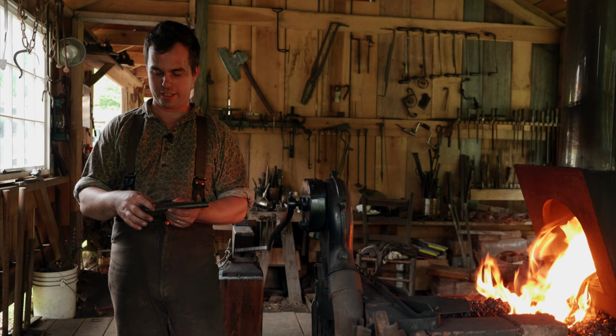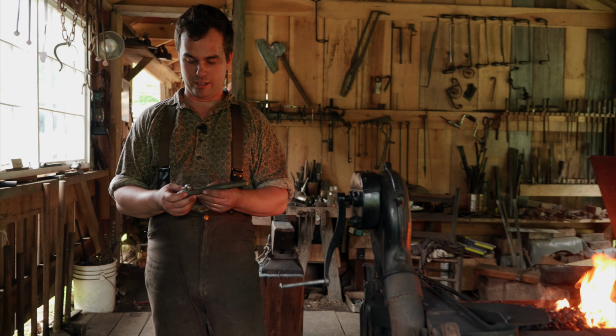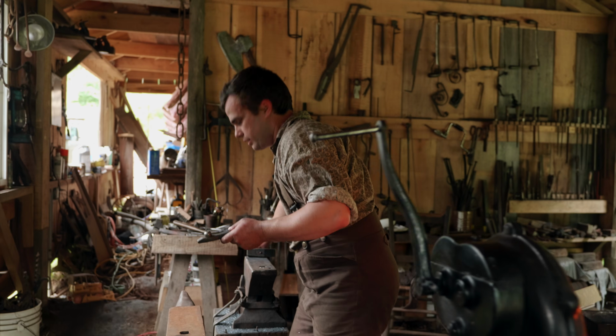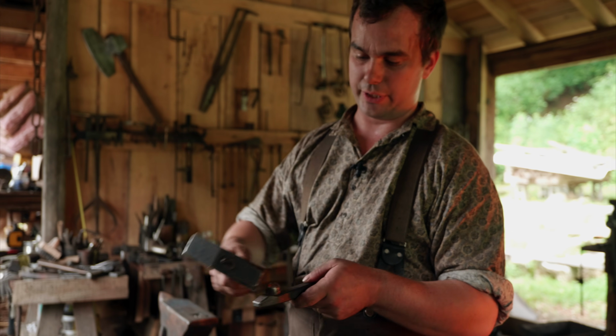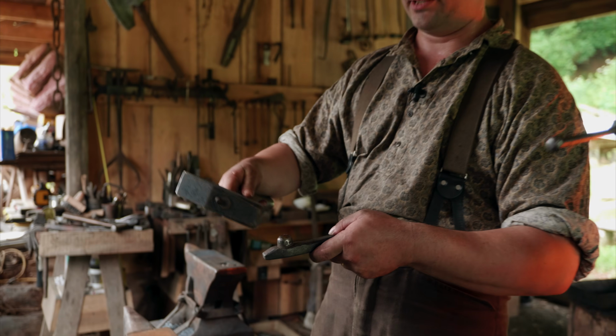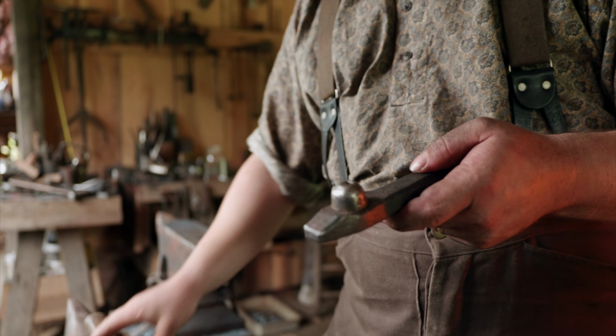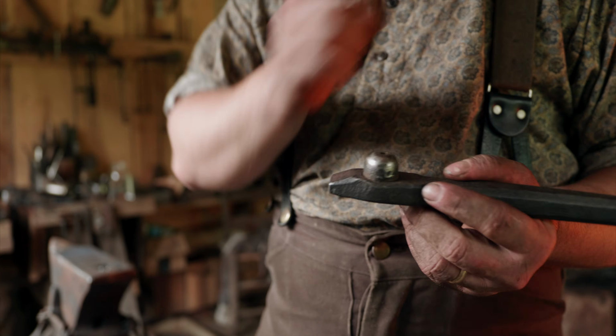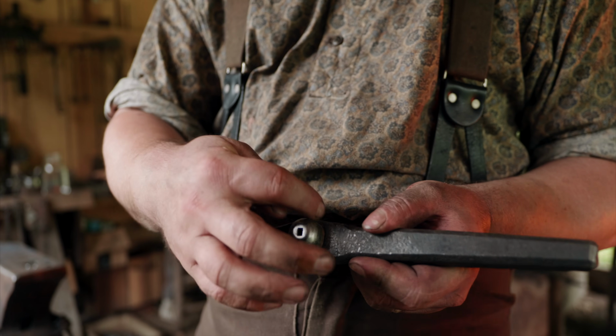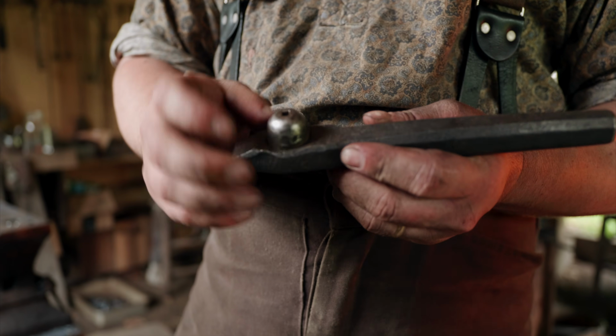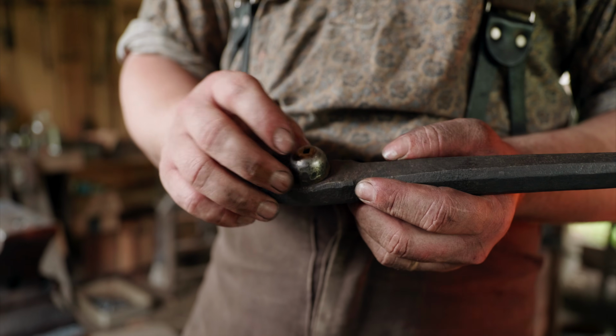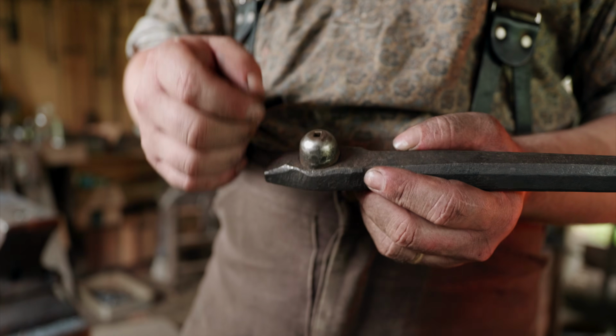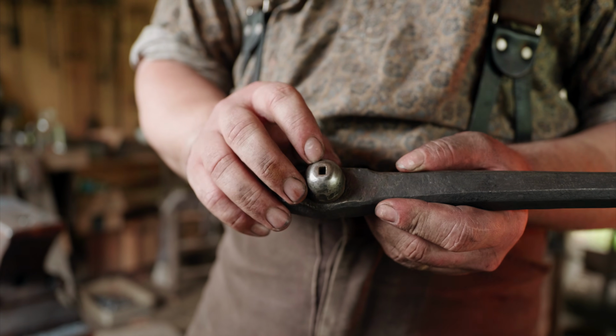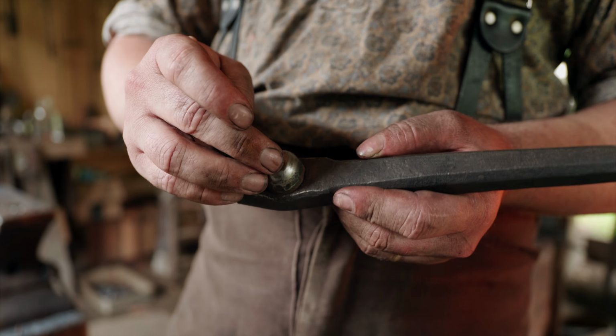So the high dome shape of this header is so that you have plenty of clearance for the hammer when making faceted blows on the nail head. And so that's what I'm doing right now on the end of this piece of steel, is I'm trying to prep the end of the steel to form this shape or something similar. I'm going a little bit smaller because this header we're making is for smaller nails than this one, and because I want to account for any squish that we get while I'm hammering on this during forge welding.